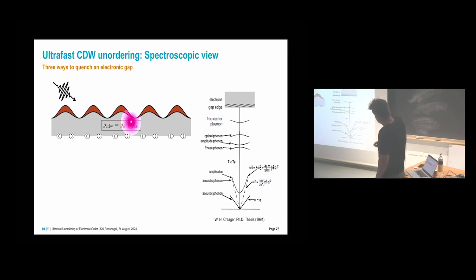So my point would be, what is a charge density wave? It in essence contains two types of charge density. One electronic, which may derive from this excitonic insulator instability, and one lattice charge density, which is really tied to the atoms. So if your atom moves, then your lattice charge density moves. So you can split this up in the time domain.